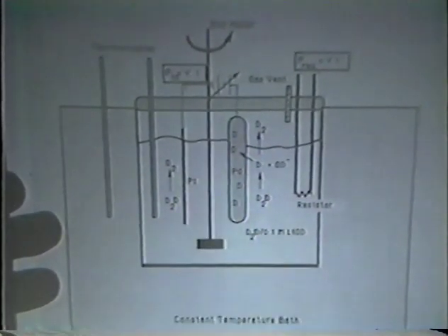The correction for this voltage is 1.54 volts. And so actually we should, if we're evolving this gas, have to apply less power here to compensate for an input power here in the absence of any excess power production by the circuit. And we stir very well to maintain a uniform temperature profile. We vary this and measure with several different thermistors at different places to ensure that.